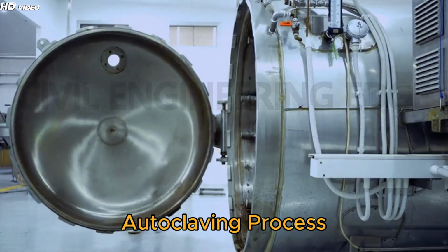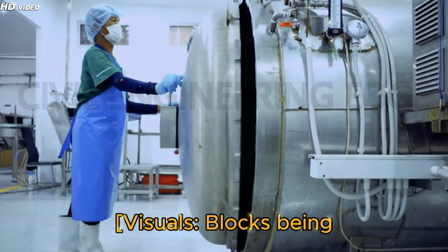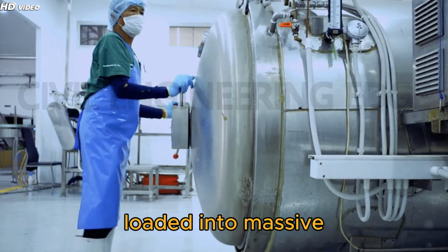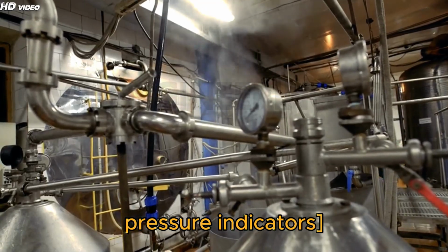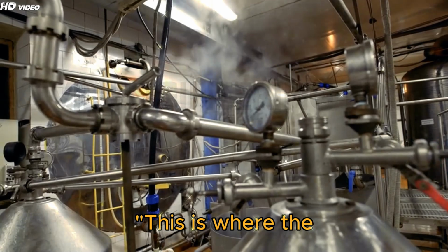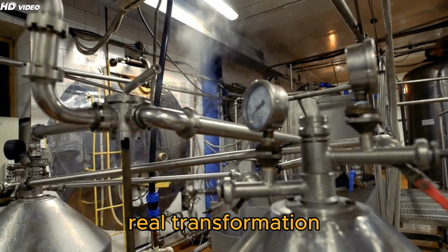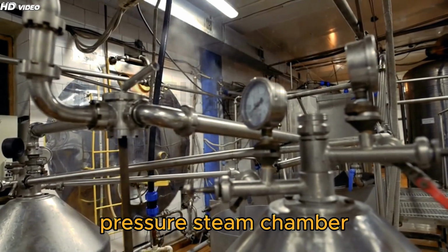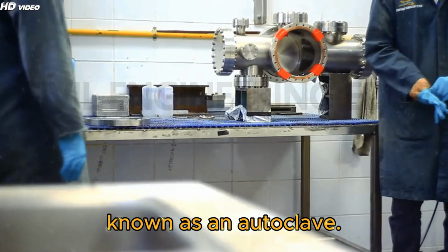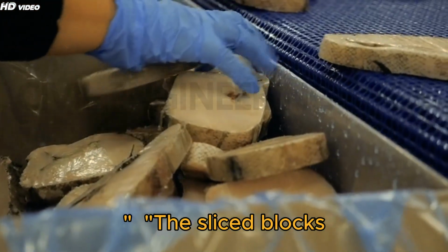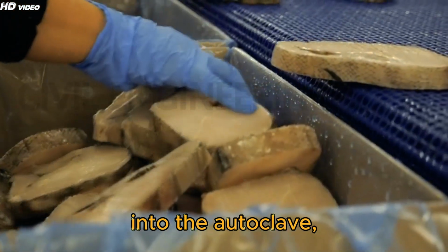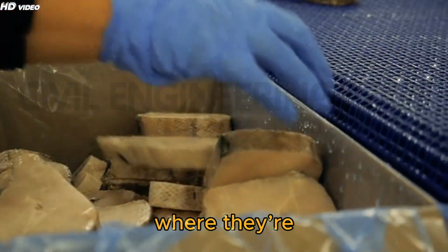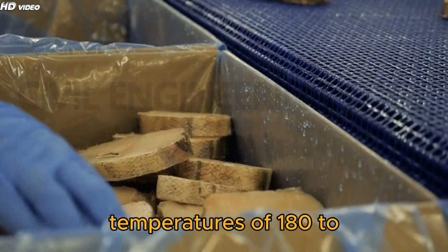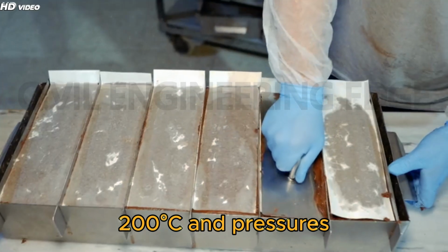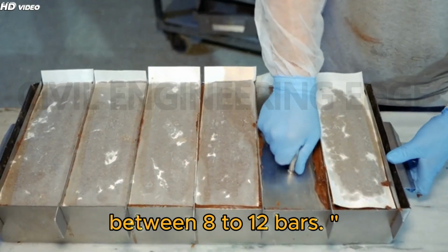Section 10. The autoclaving process. Visuals. Blocks being loaded into massive autoclaves, steam and pressure indicators. This is where the real transformation happens. In a high-pressure steam chamber, the sliced blocks are stacked and loaded into the autoclave, where they're subjected to temperatures of 180 to 200 degrees Celsius and pressures between 8 to 12 bars.